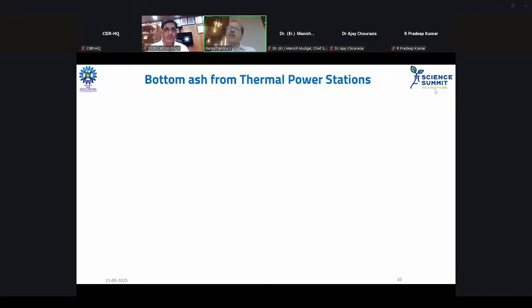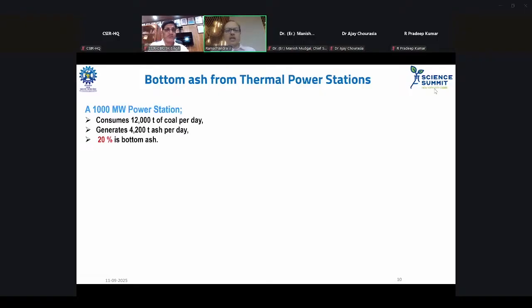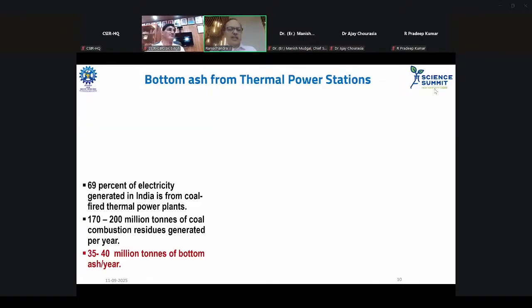Bottom ash is available in our thermal plants in a very big way. As we know, a 1000 megawatt power station would consume about 12,000 tons of coal per day. It generates 4,200 tons of ash per day, out of which 20%, around 800 to 850 tons, is the bottom ash that is produced. Whether we like it or not, 67 to 69% of electricity is generated in India from coal-based plants, and therefore we have more than 35 to 40 million tons of bottom ash produced per year.